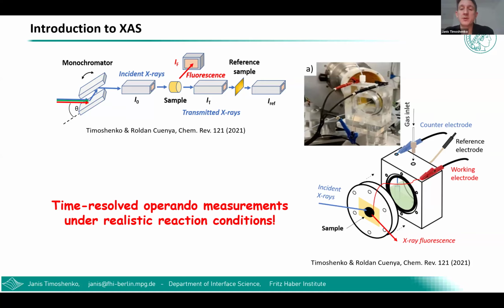What's nice here is that, with the development of synchrotron radiation facilities, we can do these experiments with very good time resolution, up to 1 second per spectrum. In this case, we can track really fast changes in the catalyst and obtain information about the changes in oxidation state, but also about the changes in its local structure.